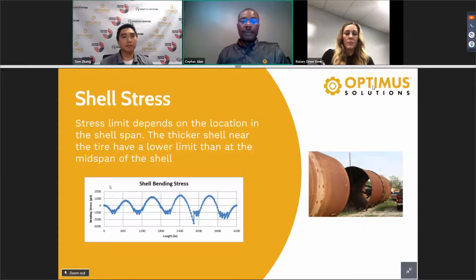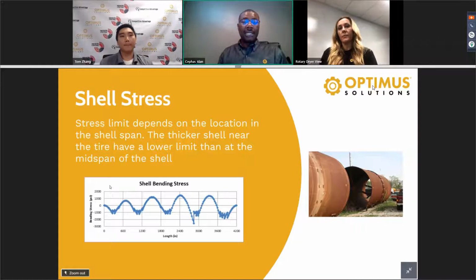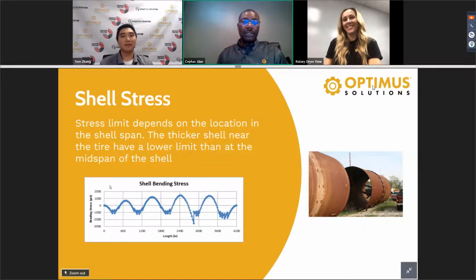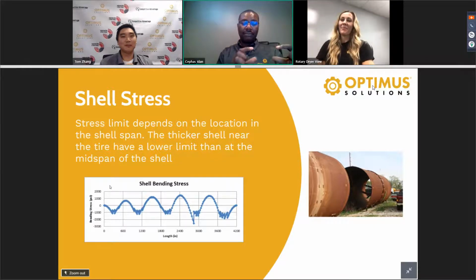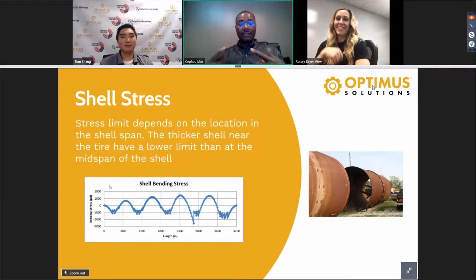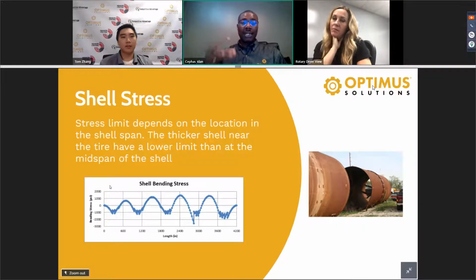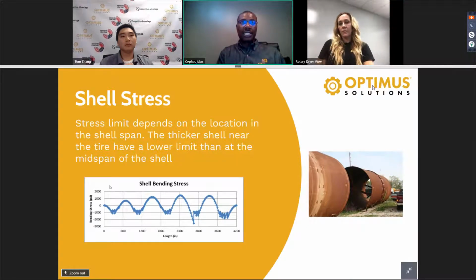Yeah. So my thinking is that it's basically based on fatigue stress analysis. And from the studies that we've done and based on the standards that we have been using, the limits are thickness dependent. So where you have tires, you have thicker shells, whilst in the mid spans, you have thinner shells. What the standards recommend is that as the shells become thinner, the limit actually increases. And as the shells become thicker, the limit decreases. So for example, a 1 inch thickness of a shell might have maybe a limit of say 2,500 psi, whilst 3/4 might have maybe 3,000 psi.